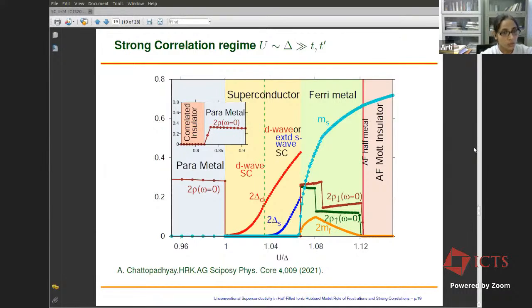And in between, there is a small range of electron-electron interaction where both the D wave and the extended S wave superconductivity are almost degenerate. Now, the interesting feature about this phase diagram is that the superconductivity is sandwiched by the paramagnetic metal and the ferri metal on the other side, although the superconductivity is mainly induced by spin exchange interactions in this model.